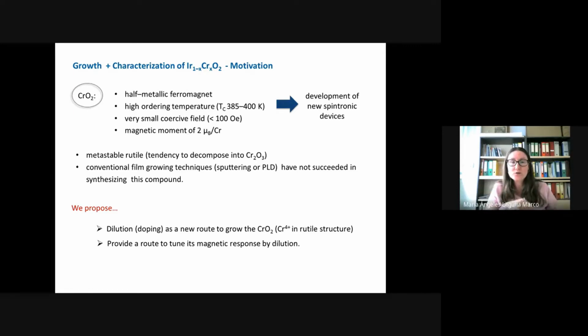However, chromium dioxide, which crystallizes in the rutile structure, is also a thermally unstable phase with a tendency to decompose into the antiferromagnetic and more stable chromium-2 oxygen-3 phase. In addition, conventional film growing techniques such as sputtering or PLD haven't succeeded yet in synthesizing this compound. This is clearly a major drawback for the development of spintronic devices.